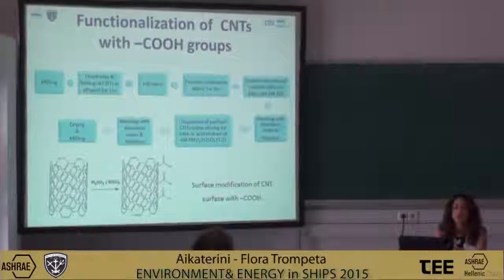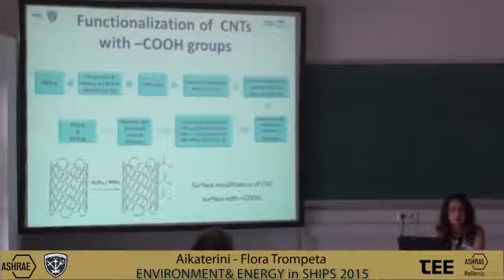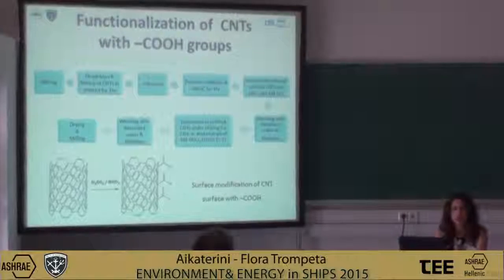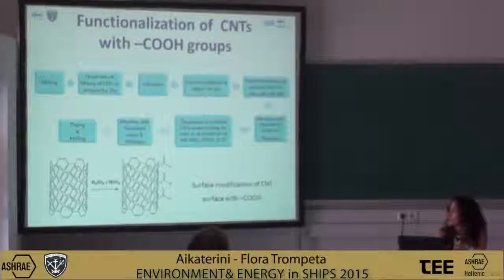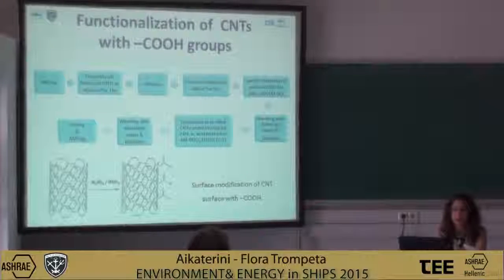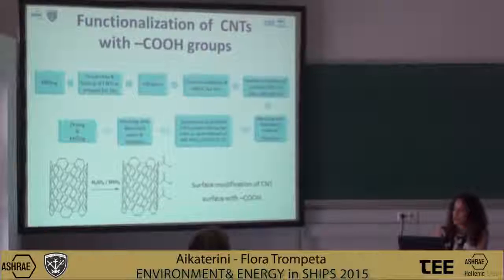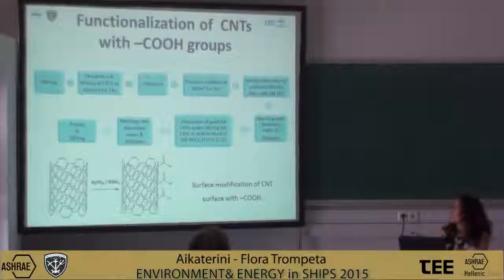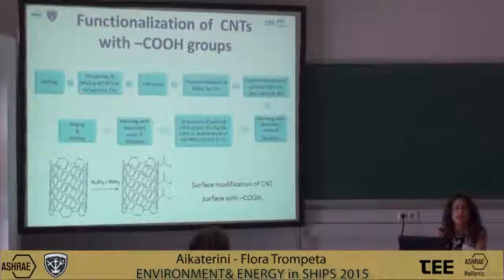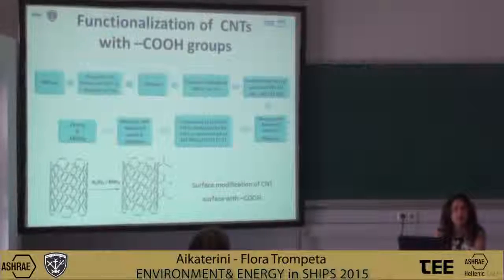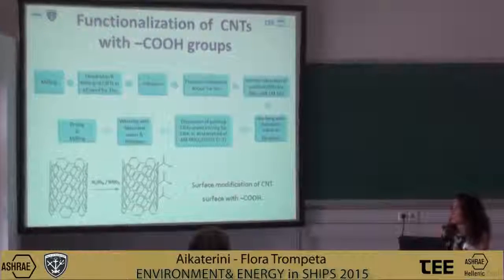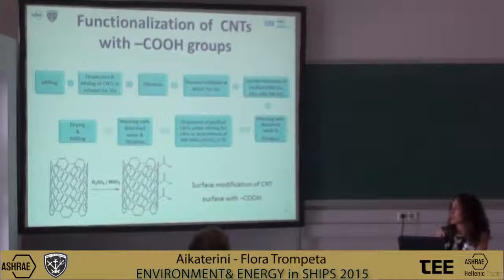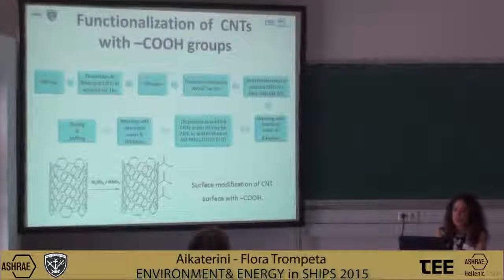The first one was the adding of carboxyl groups on the sidewalls of the CNTs. The procedure that took place was this that is described in the flowchart. And a very important step was the acid mixture of sulfuric acid and nitric acid in a ratio 1:3 that enables the addition of the carboxyl group on the sidewalls of CNTs, as you can see in the schematic representation.